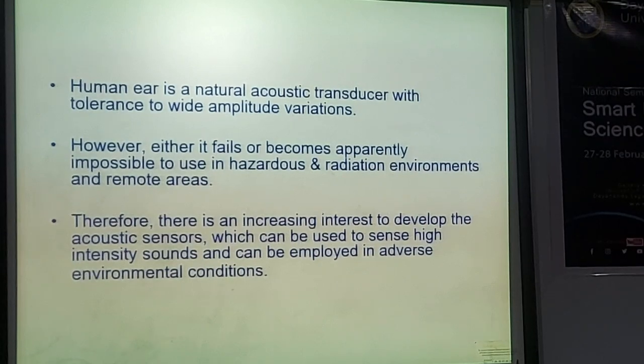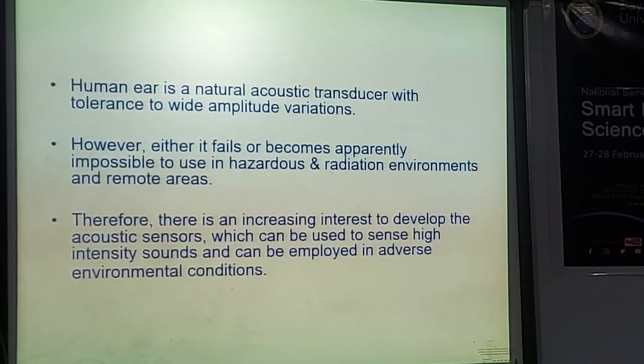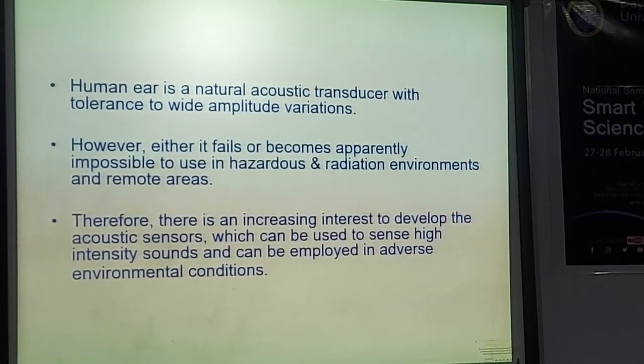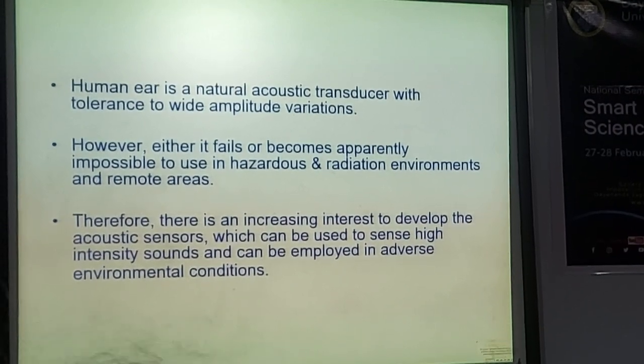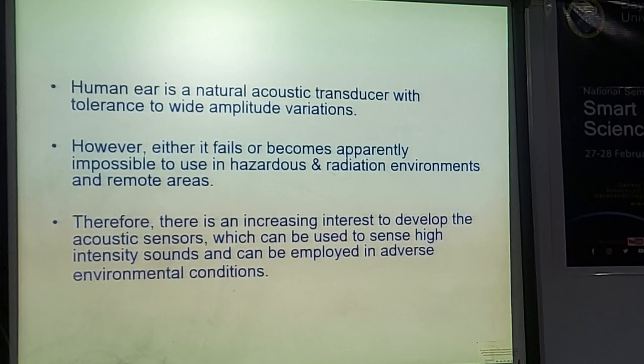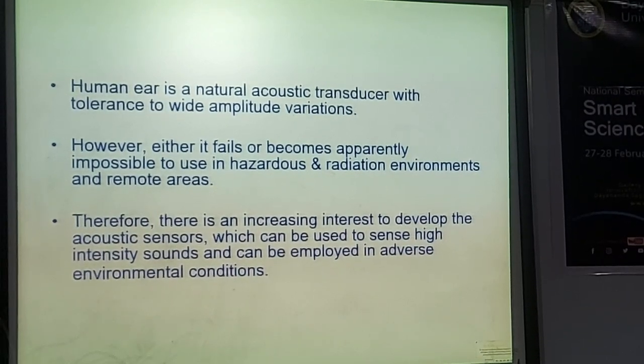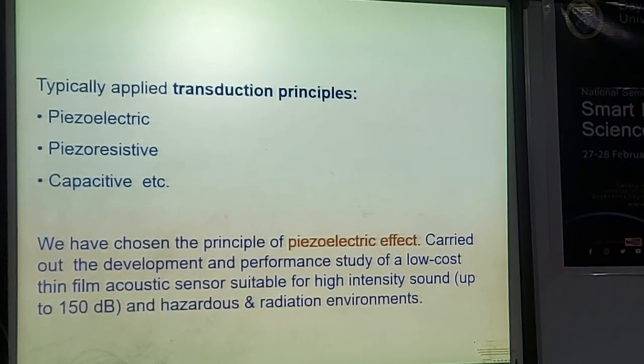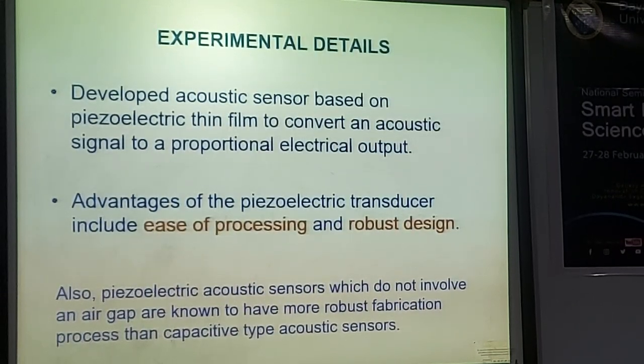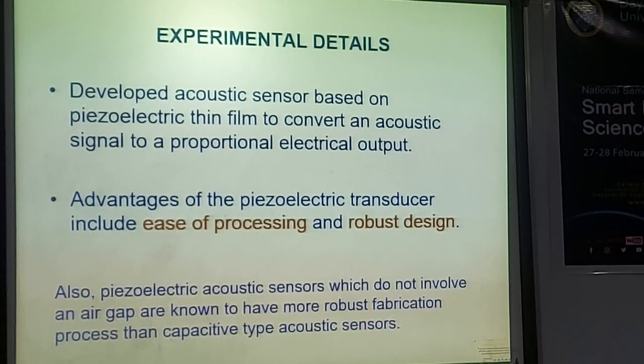In fact, the human ear is a natural acoustic transducer with tolerance to wide amplitude variations. However, it either fails or becomes impossible to use in hazardous and radiation environments and remote areas. Therefore, there is an increasing interest to develop acoustic sensors which can be used to sense high intensity sound and can be employed in adverse environmental conditions. With this in view, we developed some acoustic sensors. Typically, the transduction principle used in acoustic sensors can be based on piezoelectric, piezoresistive or capacitance phenomena. What we have chosen is the principle of piezoelectric effect, and carried out the development of low cost thin film acoustic sensors suitable for high intensity sound up to 150 dB. So, we developed the acoustic sensor based on piezoelectric thin film to convert acoustic signal into proportional electrical output.